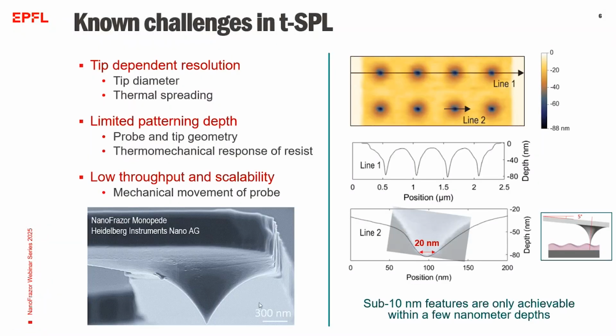Unfortunately, despite these advantages, challenges remain. First of all, the resolution depends on tip diameter and thermal spreading, which can consequently impact the written feature size and repeatability as well. Additionally, the maximum patterning depth for high-resolution grayscale pattern is typically limited to below 100 nanometer because of the tip geometry and the polymer's thermomechanical response.